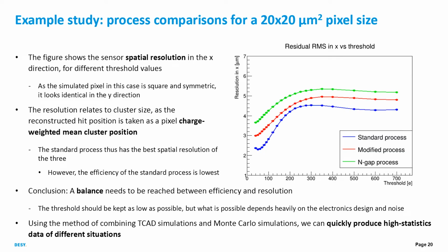Now, the resolution is very related to cluster size. This figure shows resolution in the x direction, but it would be the same in the y direction because the pixels are square and symmetric in this simulation. But since the reconstructed hit position is taken to be a charge-weighted mean cluster position, if we have a larger cluster, we get a better position interpolation. And what we can see then is that the standard process, so lower is better here, has a better resolution than the other two.